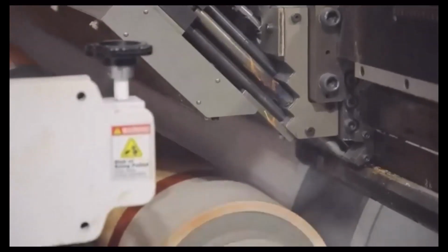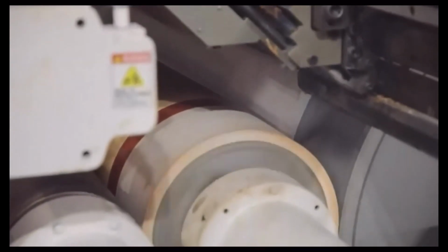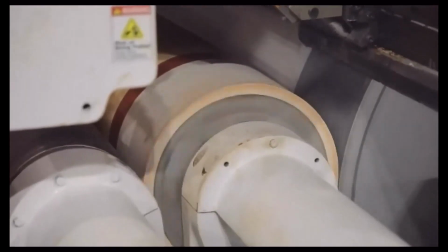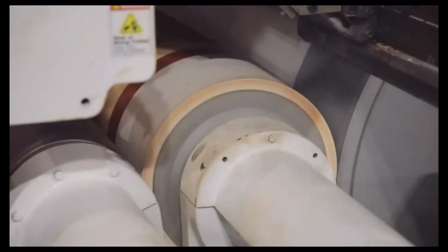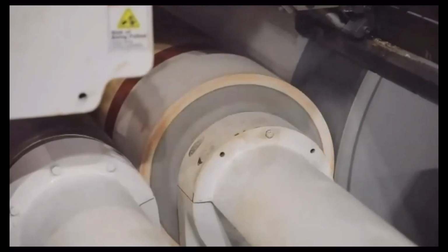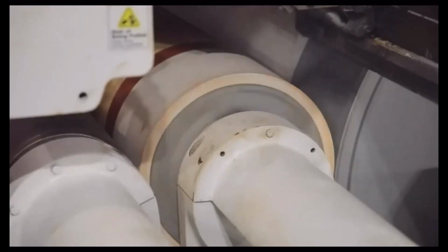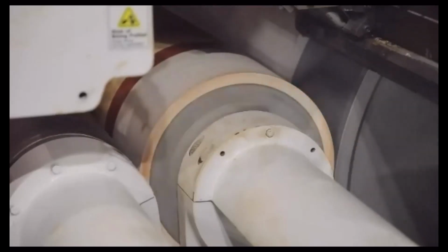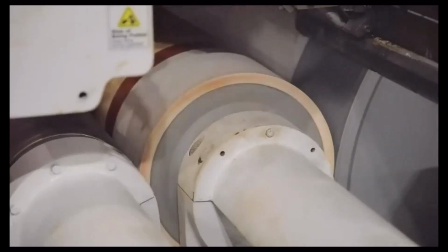Laminating station is another critical assembly in this process, where the primary substrate is laminated with the secondary substrate using molten polymer under nip pressure. The chill roll, the big roll which you see on the right-hand side, around which the laminate is wrapped, cools the molten polymer very, very rapidly. Thus, this roll is highly heat conductive with very low thermal expansion. It is a double shell design with spiral flutes with water circulating through it for minimum temperature variation across the width. This is an important factor to ensure a high and consistent bond strength.